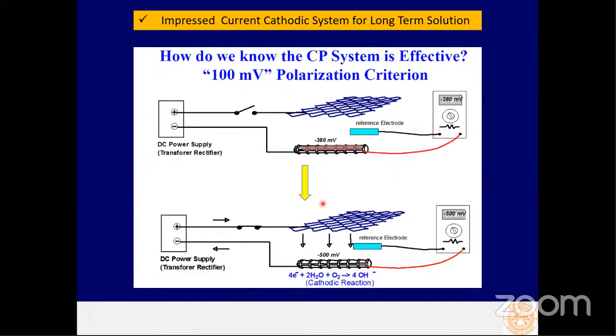And usually when we decide the potentials and voltage of this circuit, we use the polarization criterion where we keep the polarization at about 100 millivolts throughout the pier, so that we ensure that there is no more corrosion problem in the pier for this bridge.